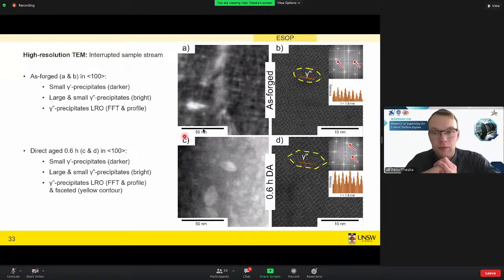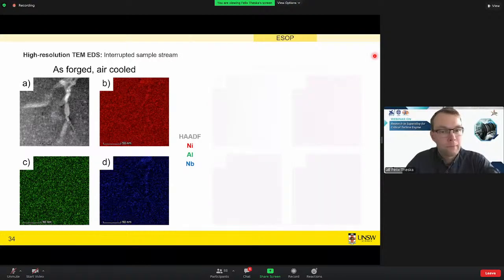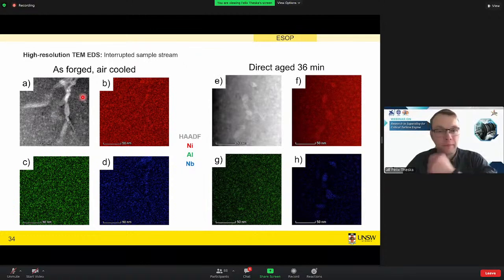It shows that the difference between as-forged and direct aging in a very short time, only 0.6 hours. But if you also see the precipitations and the dislocation density, actually in the next slide, perhaps the structure is also similar. Does it mean that the direct aging is because of the very short times, or what else? And how did you prepare the samples? I just worried that if you prepare them by FIB, there is some contamination that will affect the precipitation in your structure.